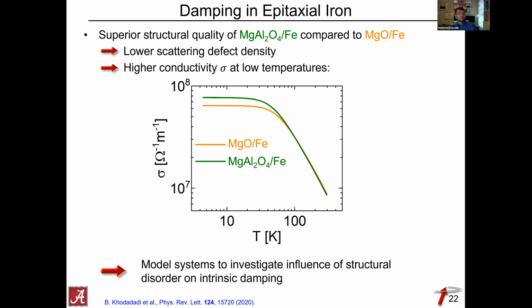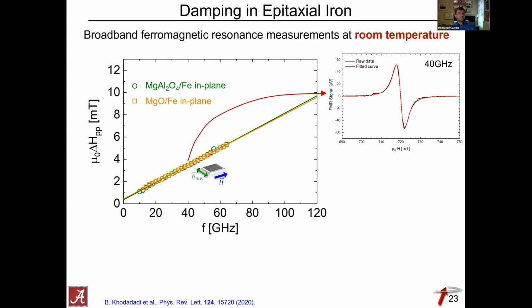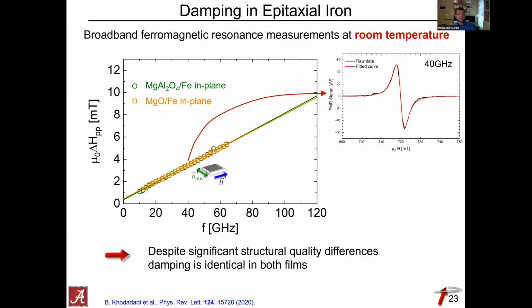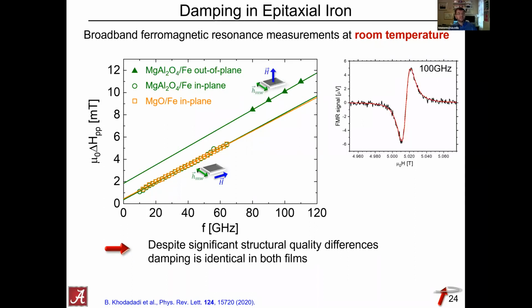Let's take a look at what we measure at room temperature. These are measurements of two iron films measured in plane, one on magnesium aluminum oxide and the other on MgO. Like I said, they are structurally very different, but at room temperature we get exactly the same line widths as a function of frequency. So their damping is virtually the same. Now you might say, this is measured in plane, maybe you are just limited by two magnon scattering. Well, that is not the case, as we can see in this graph. We also did out-of-plane measurements where two magnon scattering is absent, and we get again the same damping parameter.